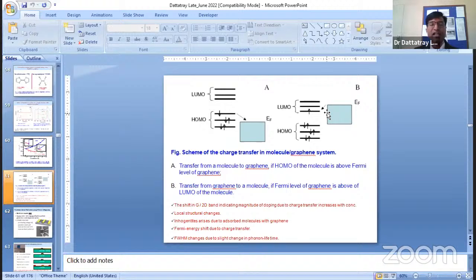The changes arise because of this structural change, and then there is a slight shift in the Fermi energy level, and this FWHM is also monitored. This was also found to change because of the change in phonon lifetime and all these things. And with this addition of TTF and TCNE, we also expect a small opening of the band gap, which is absent in pristine graphene. So it's possible that a small band gap can open between the conduction band and valence band.